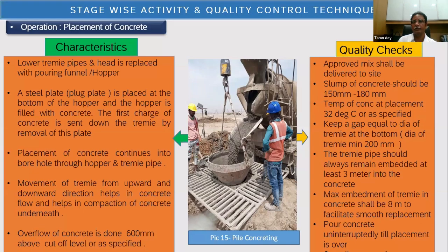Say your placement time for concrete is 3 hours. So the retention of concrete should be maintained at least until 3 hours. The slump or flow should not fall below 150 even after 3 hours for the first charge. So the concrete should remain workable until placement is over. After some time, the initial set should start. If the initial set starts earlier, then you will face problems in placing the concrete of the subsequent batches.